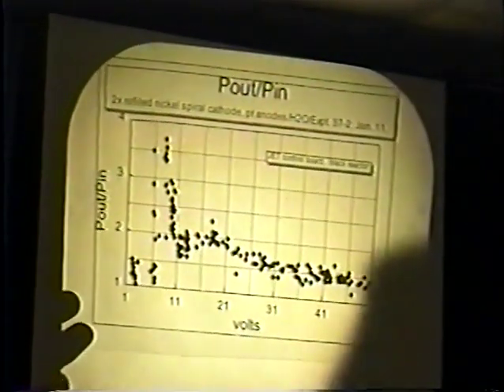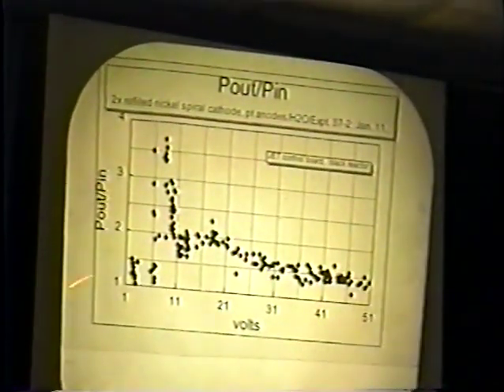Here, for example, this is a platinum system. What we do is this system was cold work nickel wire in the shape of a spiral. We use, this was paired platinum. This isn't the best configuration we have now, but this was the configuration back around '94. And what we find is that the excess heat goes to a peak and then comes down.